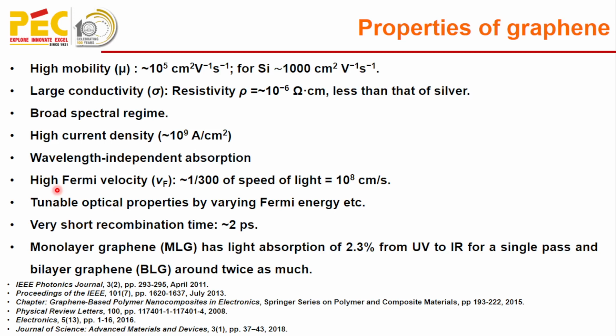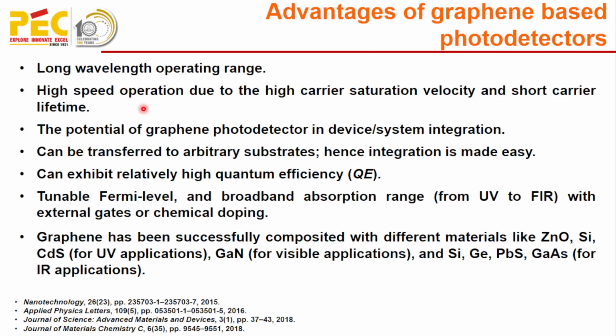So we have the advantages of graphene-based photodetectors. Graphene-based photodetectors can operate at long wavelengths. They have high-speed operation due to the high carrier saturation velocity and short carrier lifetime. There is potential for graphene photodetectors in device and system integration. They can be transferred to any substrate, so you can say integration is easy. They can exhibit high quantum efficiency. Graphene photodetectors can tune the Fermi level by external gate voltage or by applying chemical doping, so we can achieve a broadband absorption range from ultraviolet to far infrared.